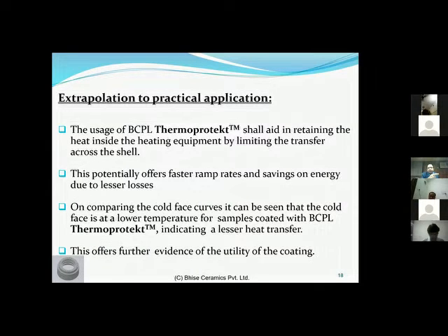As we saw in the earlier case, the steady state temperature was attained in about 11 minutes versus 21 minutes taken in the control. You can have more heat work on the components inside than on the insulation because of this. Again, if you see the cold face, you will have a cooler cold face. For now, the trend is that you need to have the cold face, the exterior of the furnace, be something that you can touch.